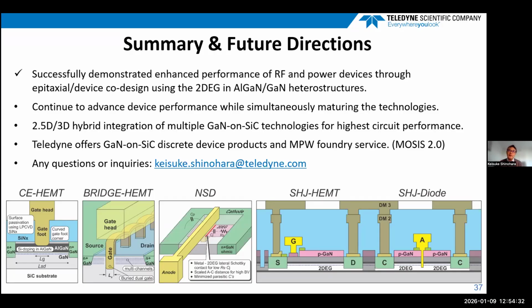We optimize the spacing between the channels in order to control the effective 3D density of the channel. Because if you make it too close, it becomes very hard to pinch off using the lateral gate. So essentially, you have to control the doping density and the distance between the channels in order to control the effective 3D density, to optimize the channel modulation efficiency by the lateral gating.